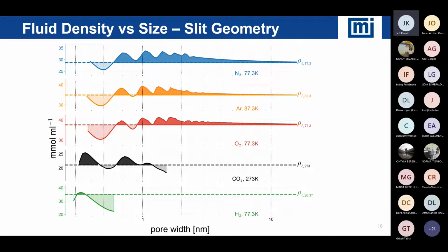And one of the areas we particularly like to look at all the time is, if I have nitrogen, and you see nitrogen on the top in blue, how dense is the nitrogen in the pore system? So if I'm at 0.5 nanometer on the left side, you notice the light blue shading. The density of nitrogen in a 0.5 nanometer pore is less than the density of bulk liquid nitrogen. Okay? And the bulk liquid densities are listed on the right side for you. Likewise, if I do the same for argon or oxygen, we've got the same behavior.